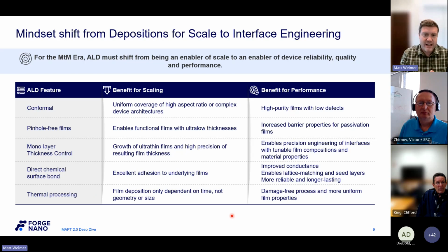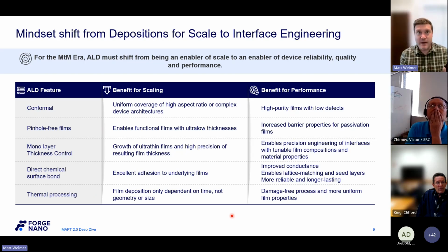It's quite basic. But if you think about a different incoming surface, let's think about just a silicon wafer. Now your surface is a native oxide silicon. That will look different than an aluminum oxide growing surface. So even there, those first few cycles will look different because of, let's say, hydroxyl density. Now let's go a little bit more complex. Let's think about a metal film, like we'll use maybe a stark example like lithium. Lithium is extremely reactive. When it sees the metal precursor for aluminum oxide, trimethyl aluminum, it actually does uncontrolled growth. It does CVD until you coat that aluminum, right? So it really depends on the incoming surface.